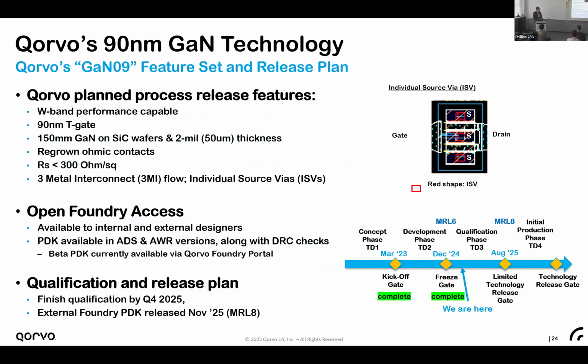It also partially answers Mohammed's question. We have the 90 nanometer gates, and we have the regrown ohmics. The sheet resistance of the wafer is typically less than 300 ohm per square. And we have this so-called 3MI flow. And especially in order to reduce the inductance, instead of increasing it, we introduce this individual source via, ISV.